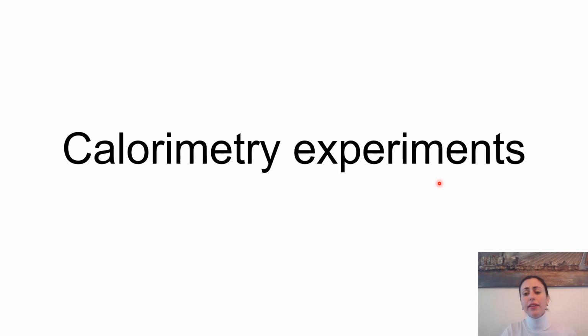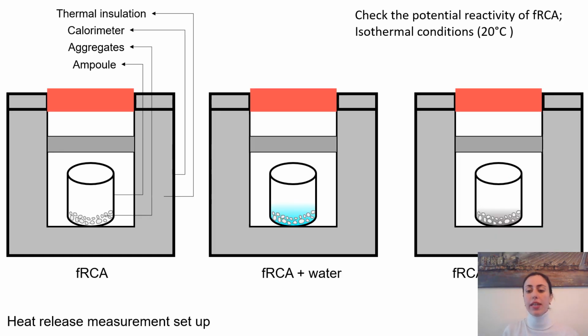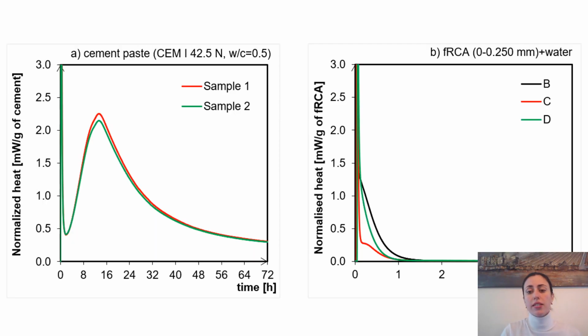Then we also checked the potential reactivity. We had three cases. We measured the potential reactivity of the recycled sand as is, where there is some moisture, then of the recycled sand and water, and recycled sand and cement. What has been found is that there is no reactivity. Basically, there is a negligible reactivity, and that is documented in the paper, where you can read more about that.